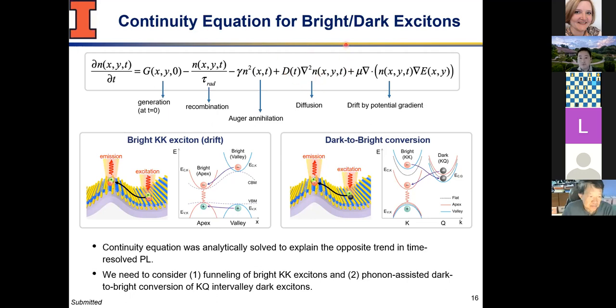So that's kind of the diffusion term. But in our case, we do need to think about the gradient of potential, because in real space, as a function of position, we have a different band gap. That band gap allows the exciton to drift. So we have a drift mobility of these excitons. It's almost like electron mobility, but we have an exciton mobility, and that's because we have an energy gradient. In a flat material, this is zero, right? So you have nothing to worry about. But in this case, you do need to worry about it.